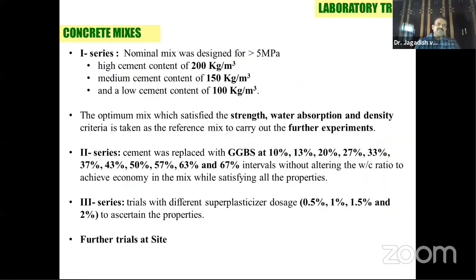When they visited 20 to 25 manufacturing plants, they understood the cement content varies between 200 to 100 kilos. Somebody is using high, somebody is using low. So the range is something like 100 to 195. We have taken the cement content between 200 and 100 kgs. So 3 mixes we have taken: 200, 150 and 100. And then we designed the mix for more than 5 MPa.